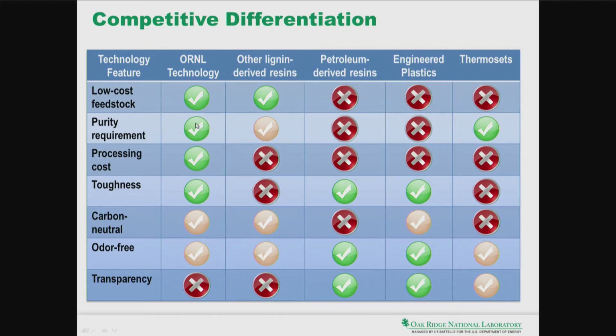Purity requirement, as I mentioned earlier, our reactivity is based on a particular functional group, and this is not a polymerization reaction truly that we are conducting in this particular set of polymeric material synthesis by extrusion process. So it doesn't have that stringent purity requirement. Of course, petroleum-derived resin or other engineered thermoplastic requires pure monomer to synthesize that material. Processing cost is easy because we are utilizing a simple extrusion technique, and other lignin-derived resin requires one-part synthesis and then again purification, further processing, and of course that is common for other resins too.